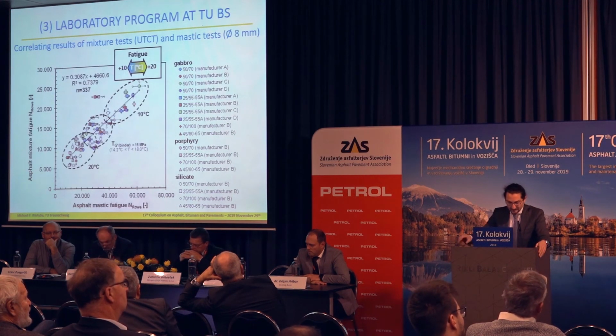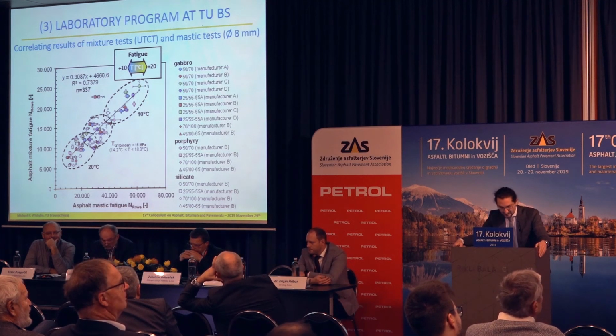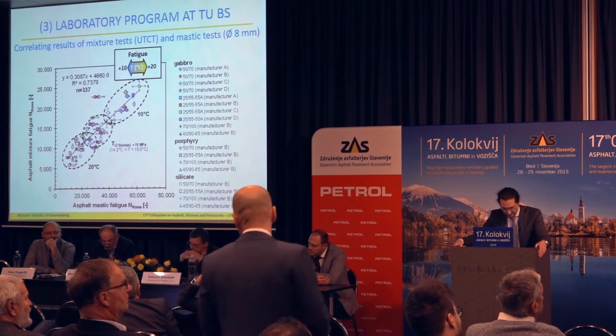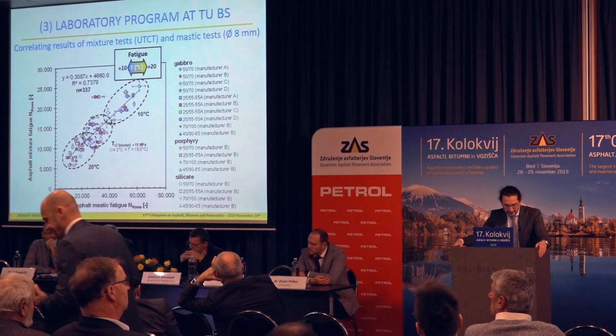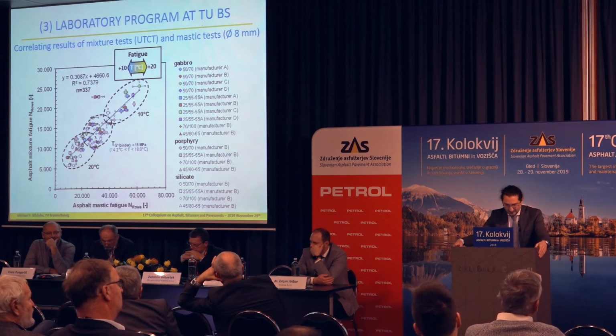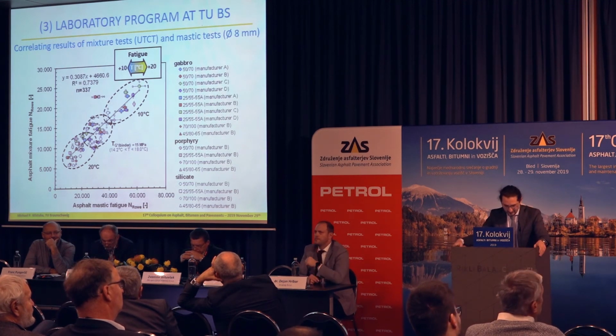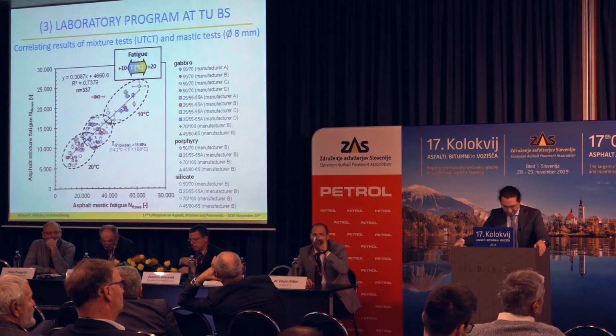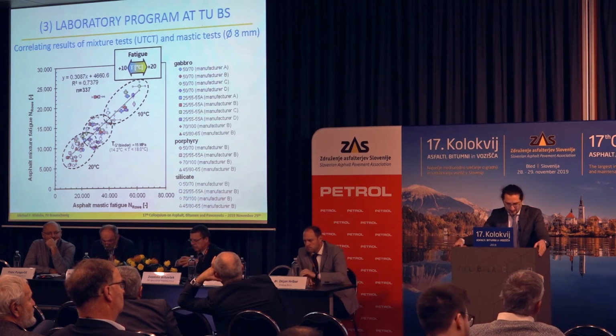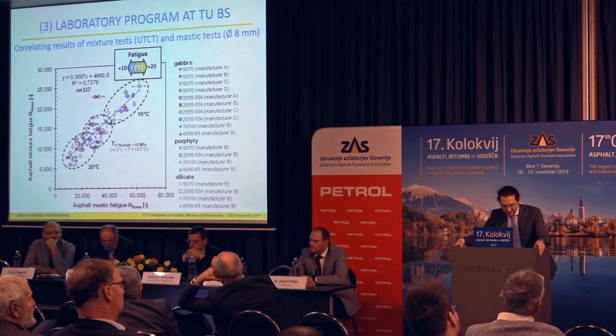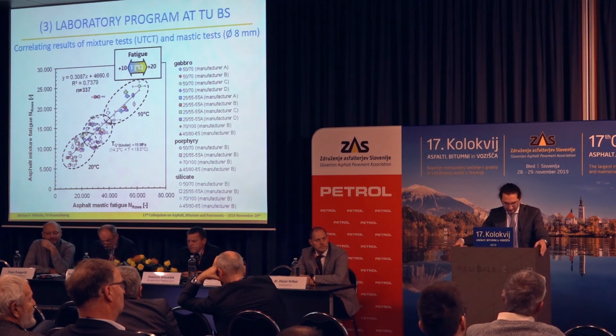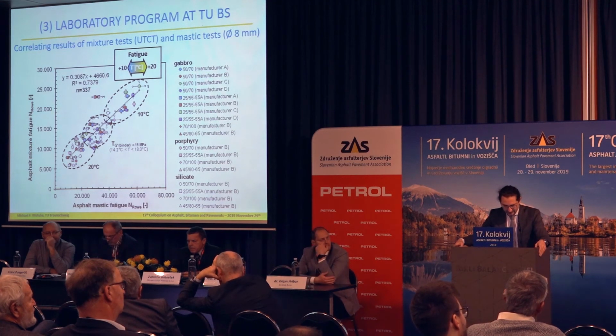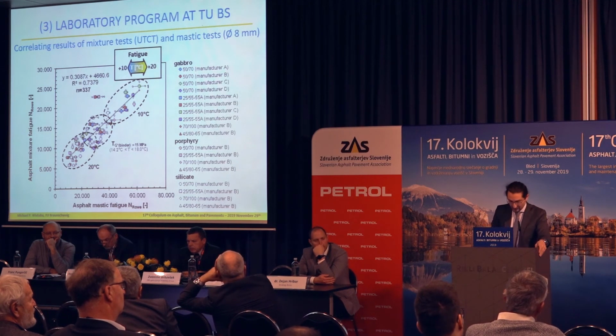So what about fatigue testing? Here you can see the results from these 18 asphalt mixtures and the corresponding asphalt mastic samples. And here the coefficient of determination is around 0.7, considering 337 pairs of test results. So the correlation is not bad, could be better. You can see some outliers shown here in red. So we are discussing at the institute, maybe there was something wrong at the asphalt mix scale. So we have to study that more in detail, and maybe the correlation becomes even better afterwards. We don't know yet.